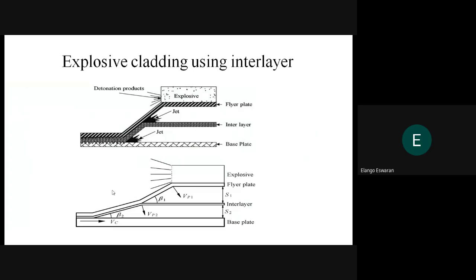And also Tamilselvan et al., while cladding titanium and steel, concluded that the formation of the detrimental intermetallic compound is imminent when the kinetic energy spent at the interface is high during the conventional two-layer cladding, that is without an interlayer. Alternatively, a strong clad devoid of intermetallic compound at the interface is achieved by employing an interlayer between the flyer and the base plate, which reduces the kinetic energy dissipation and increases the heat transfer area and also overall weldability. Here, this is the interlayer placed in between the flyer and the base plate.